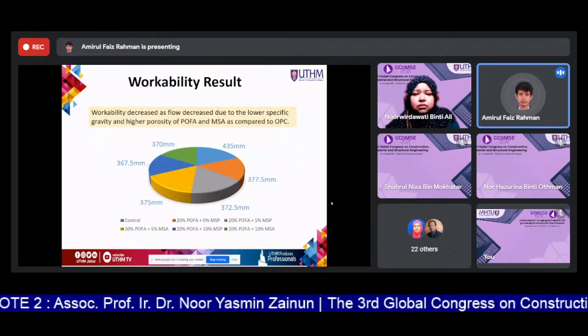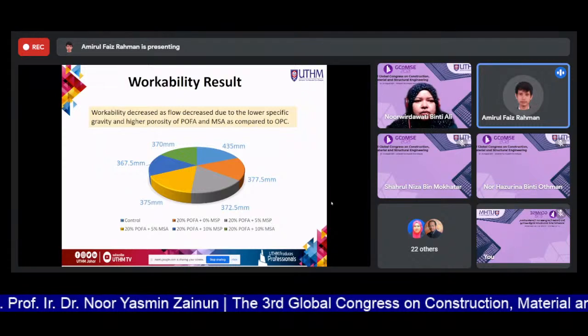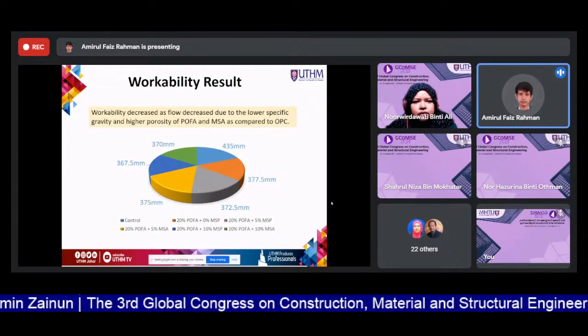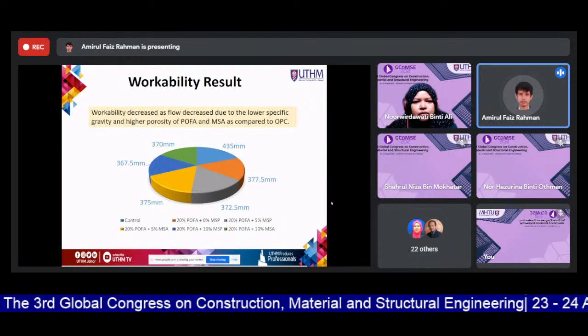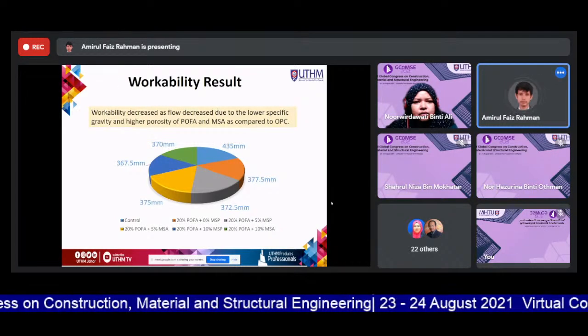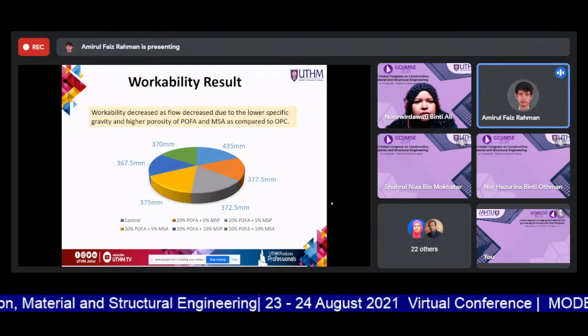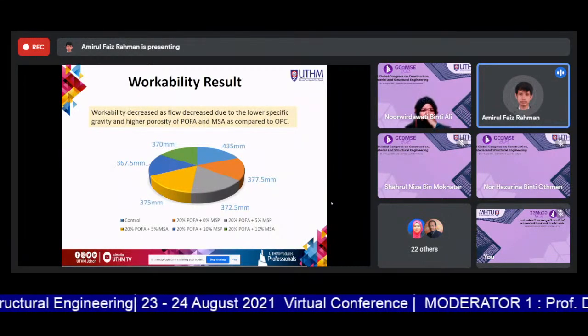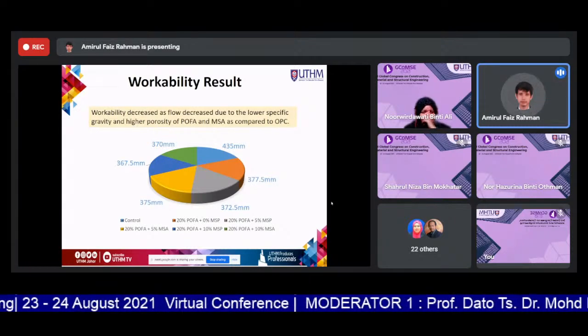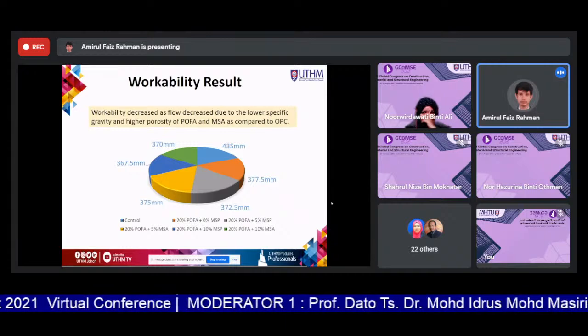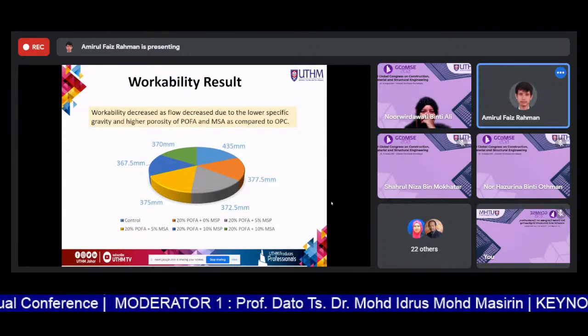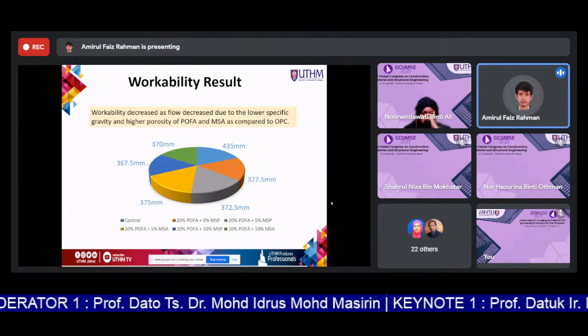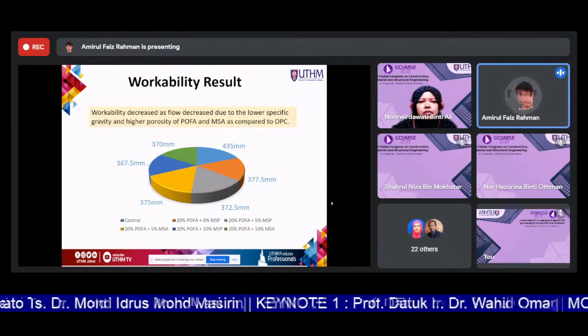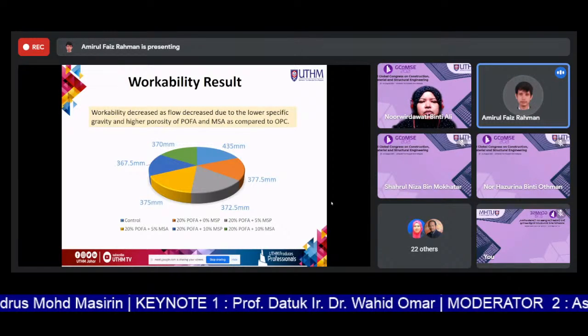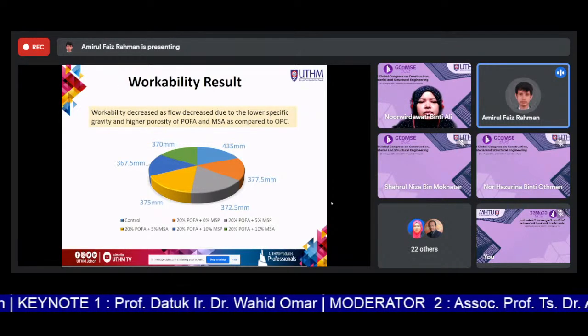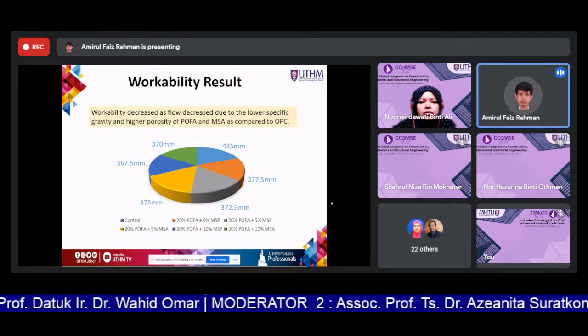Next, for the results, for the workability test we used the J-ring test with the inverted slump method, and from the result you can see that an increase in cement replacement material will reduce the workability of the samples. The workability decreased due to the lower specific gravity and higher porosity of POFA and MSA compared to OPC, with the reduction ranging from 15% to 16%.